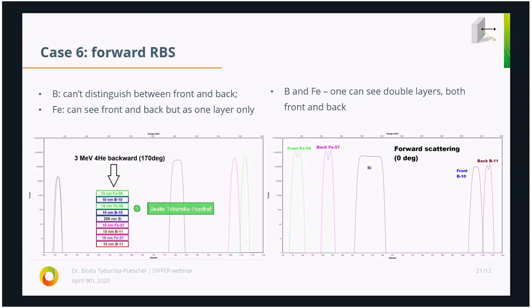As you can see in this example, we are dealing with layers which are 10 nanometers thick. So there are very, very thin layers, and you can see them with the forward scattering because of such a good depth resolution. So if some of you is dealing with membranes, this is definitely a technique which you can use in your case. I see a question.